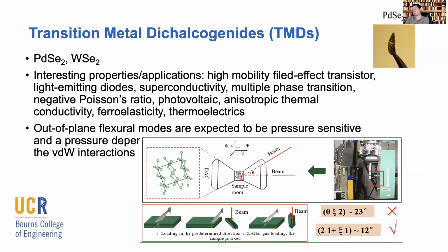This is not hard to understand because we are cutting along a direction that is not its exfoliating direction. You can imagine that we are trying to cut a layered cake with very loose bonding between the layers. We want to make a very thin slice but a very thick stack, and usually when you cut it, the thing falls apart into pieces. That did happen to us multiple times. It turns out we had to try loading this sample over 100 times until we eventually thought, oh, it might never work, and we should just deal with it and work only in the geometry that is practical for loading. But it turned out we were lucky.